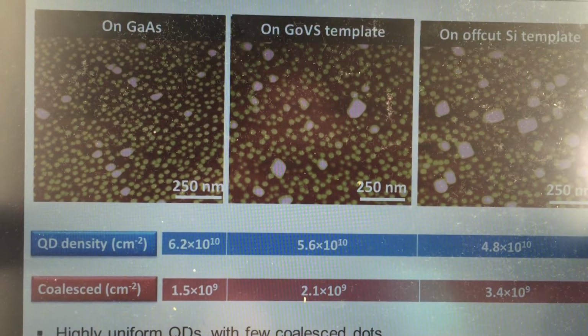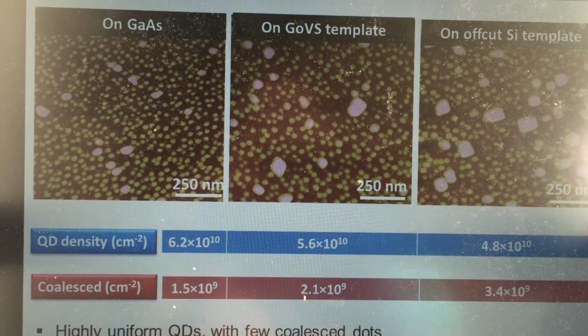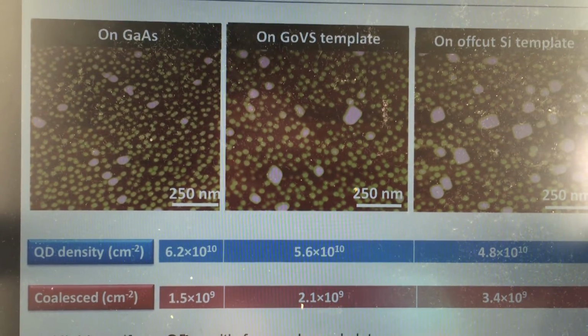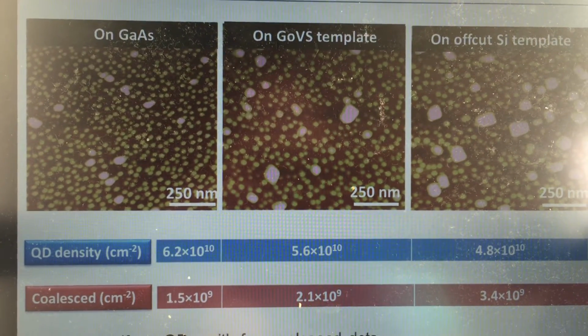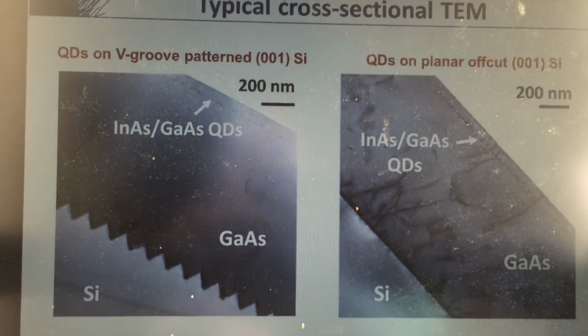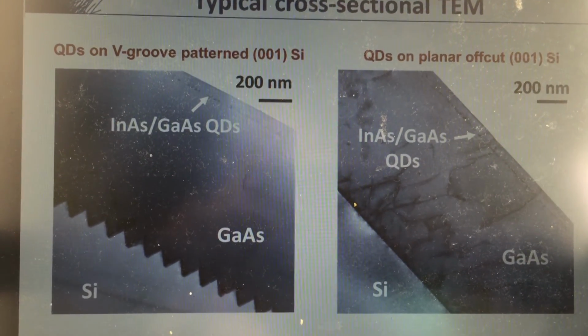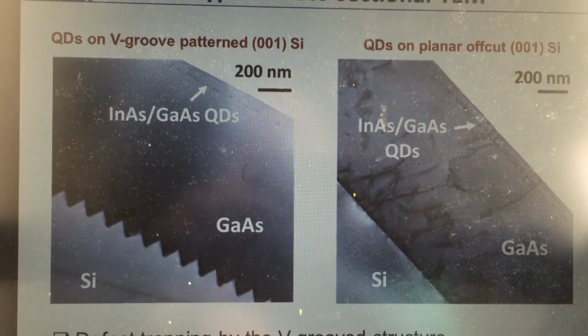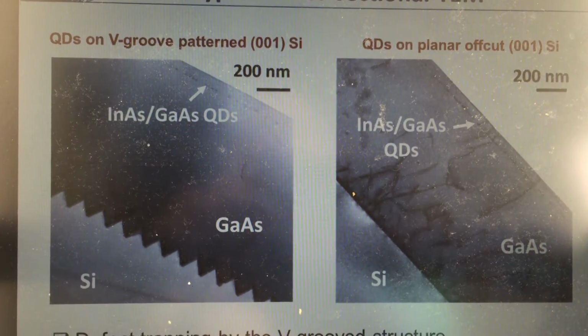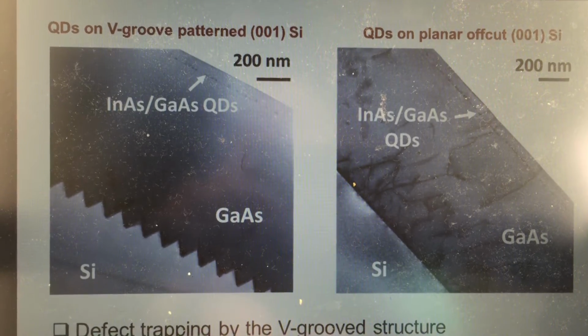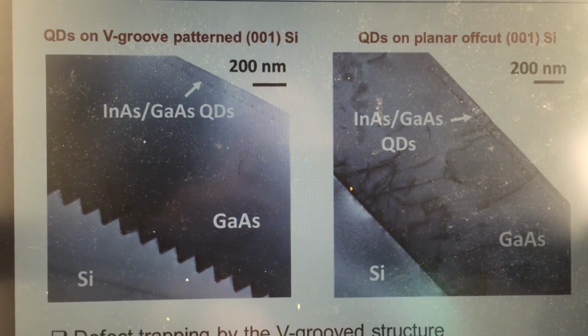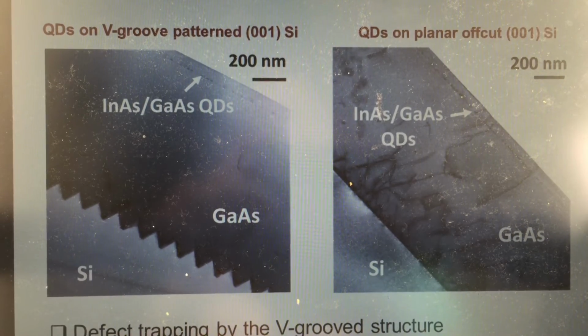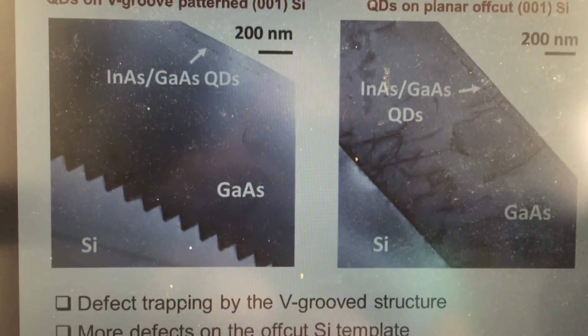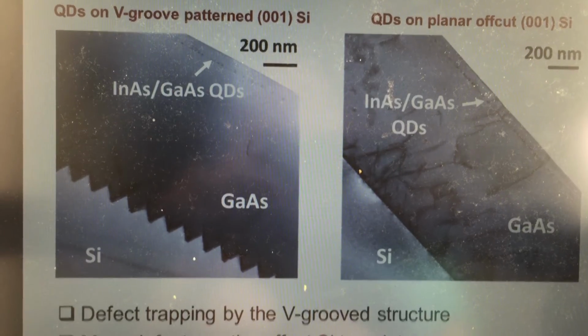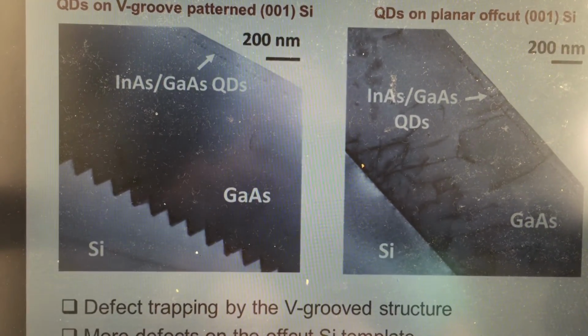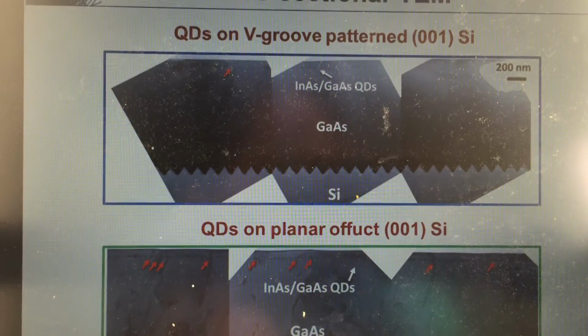The coalescence islands are slightly higher than on the GaAs substrate, but much smaller than on the off-cut silicon template, which could be attributed to the buffer condition. Here is a typical cross-sectional TEM, and we can see that on the GoVS substrate, most defects can be localized in the V-grooves, and very few can be seen in the buffer layer. On the contrary, a large density of defects was observed in the buffer, and there are many chances that the dislocation lines punch through the active region and create non-radiative recombination centers.